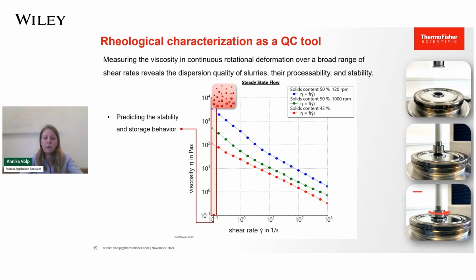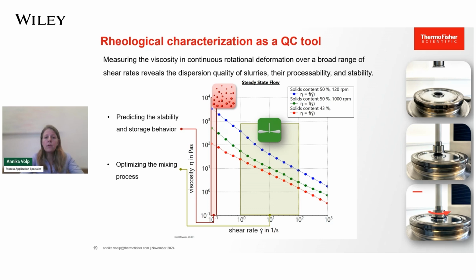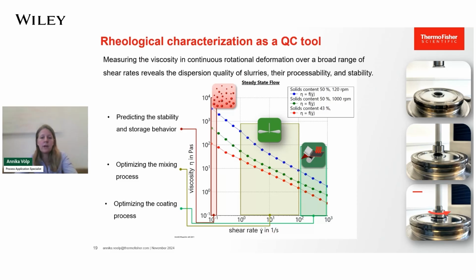In order to achieve a quick and homogeneous coating process with a constant layer thickness, the sample viscosity needs to be within a certain range and can neither be too high nor too low. So complete viscosity curves spanning from low to high shear rates are therefore extremely useful to predict various important aspects in the process cycle of an electrode slurry.